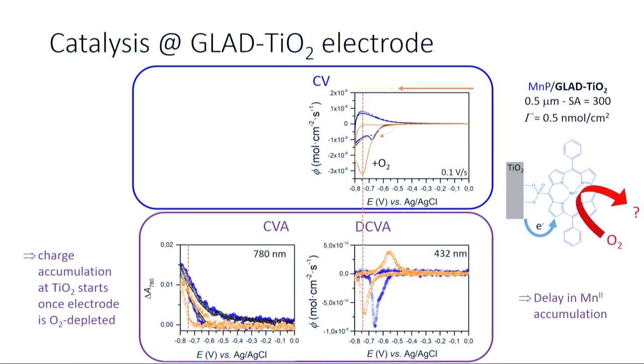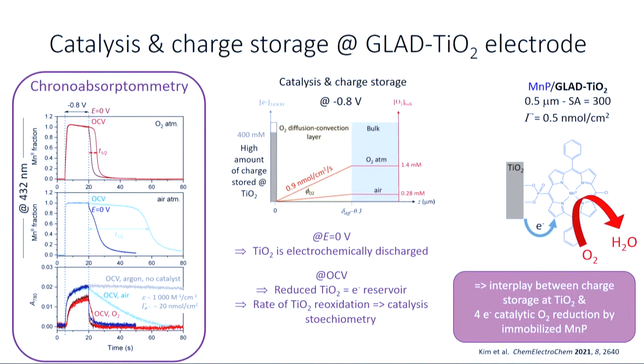Okay, so now we still have a catalytic current, so the molecule, the porphyrin, is still active for dioxygen reduction, right? We have a delay in the accumulation of the manganese 2 state, and we notice here, if we follow specifically what's happening at the titanium dioxide electrode now, okay, because now we have a technique where we follow, depending on the wavelengths, we focus either on the catalyst or directly on the metal oxide itself. Okay, so we get two different information. We deconvolute what's happening here in electrochemistry. And what we notice here is that we also have a delay in the charge accumulation at the titanium dioxide that now only starts when the electrode is depleted with dioxygen, so once we are limited by mass transport of the substrate. And to better highlight this process, we moved to chronoabsorptometric measurements.